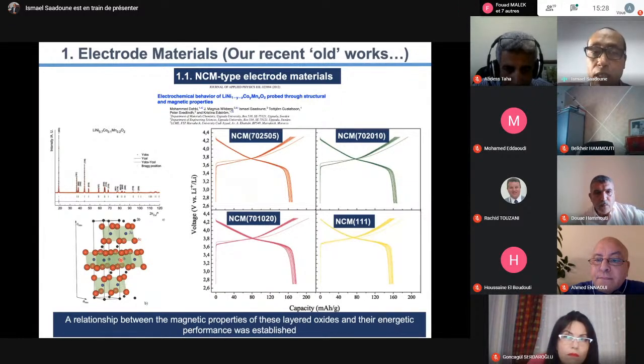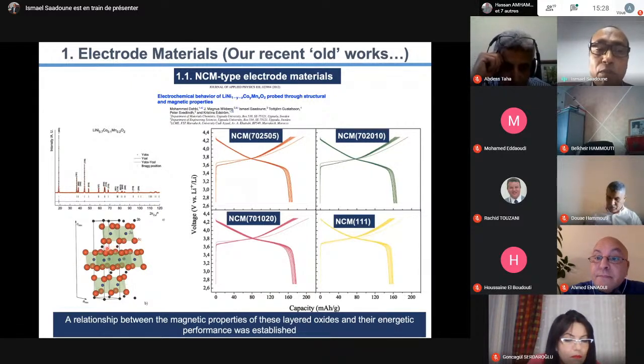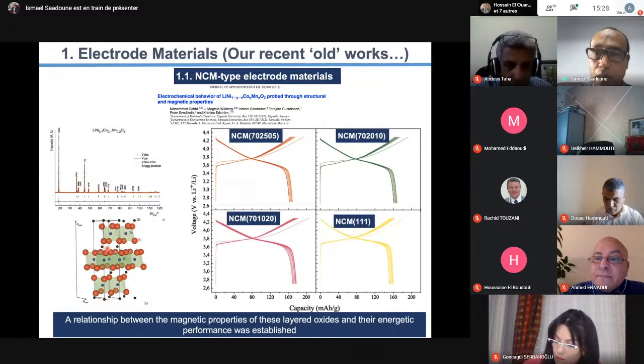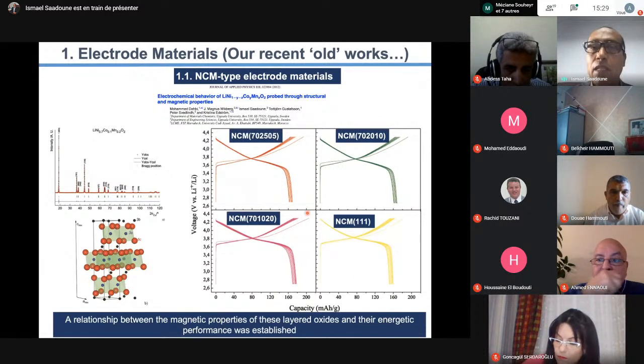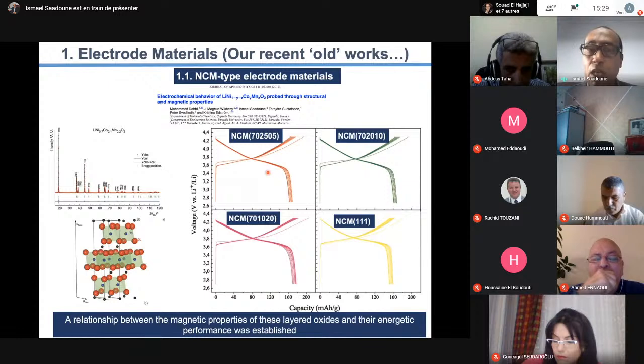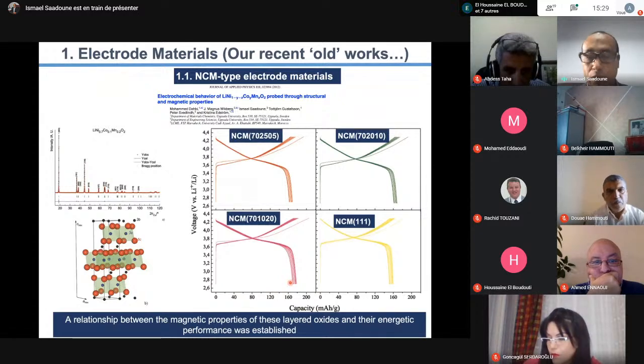So if we can correlate the magnetic properties with lithium diffusion - because if you have some frustrated ferromagnetic behavior, you get localization, and lithium cannot move very fast - here we have this in an Applied Physics paper. We showed that we can optimize the performance and capacity by deciding the content of nickel and cobalt, and by correlating magnetic properties and energetic performance.